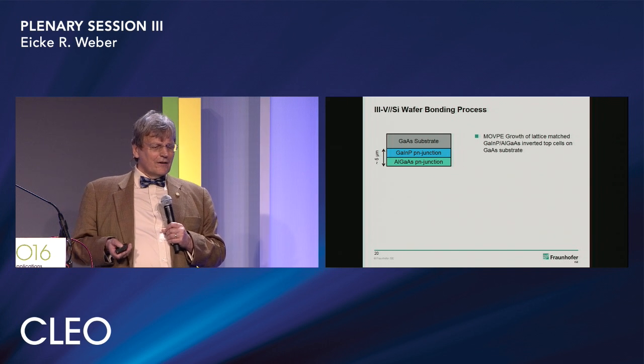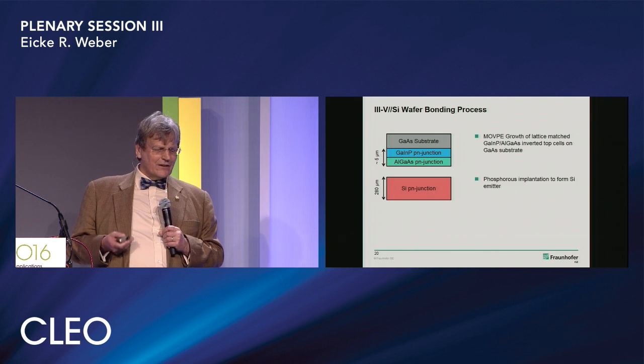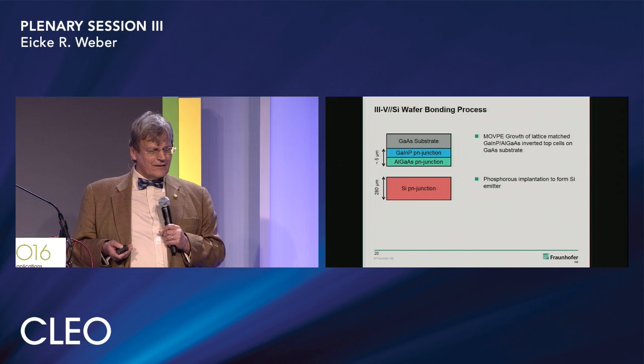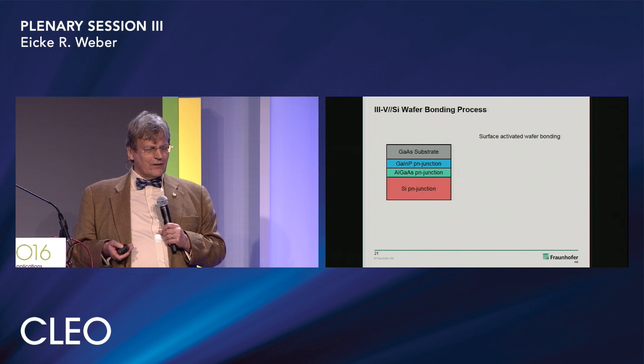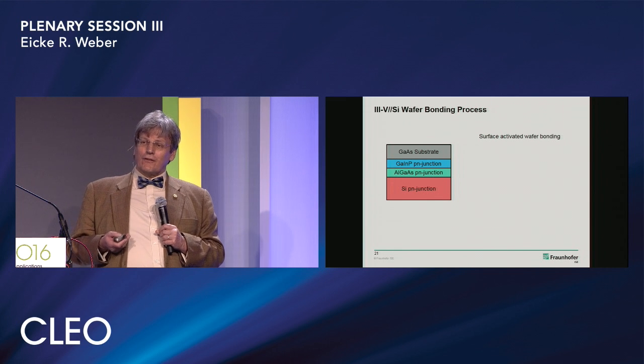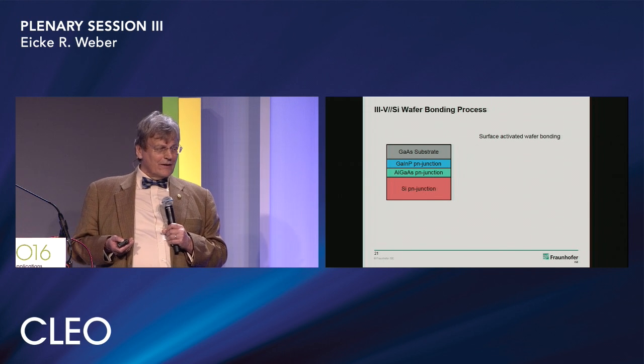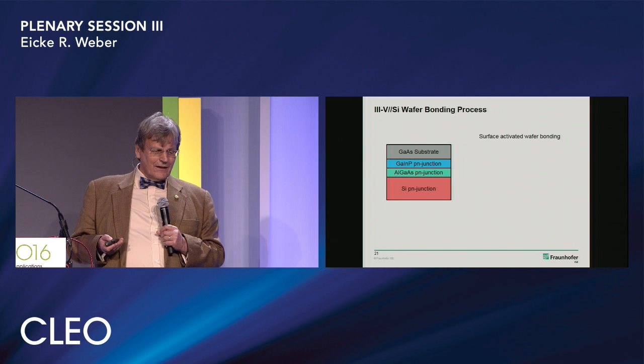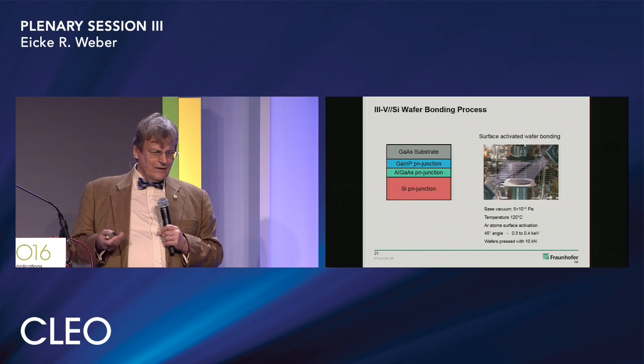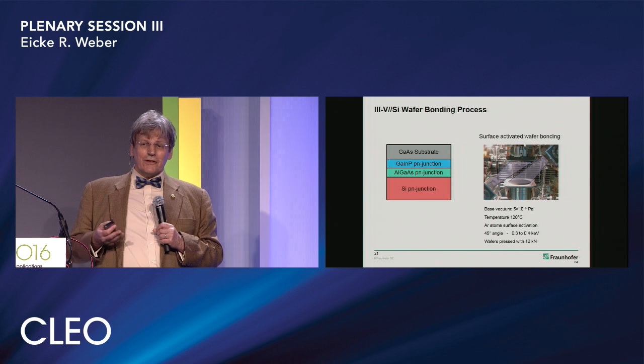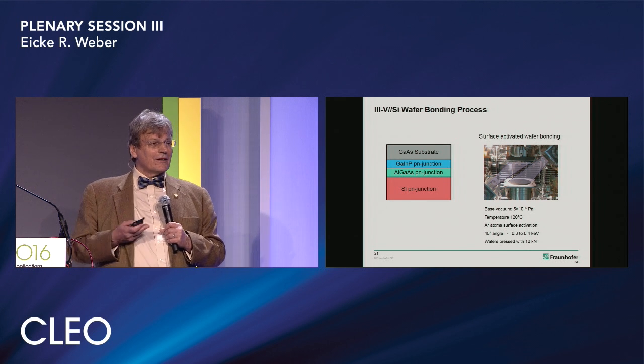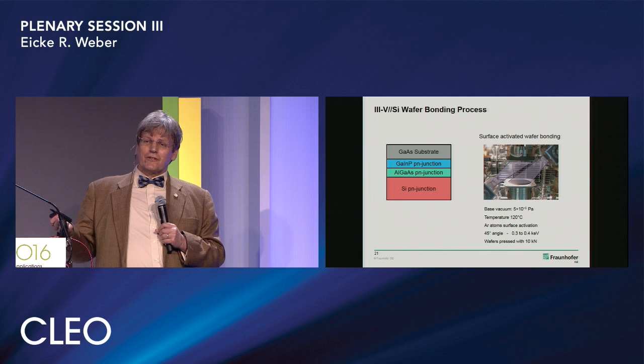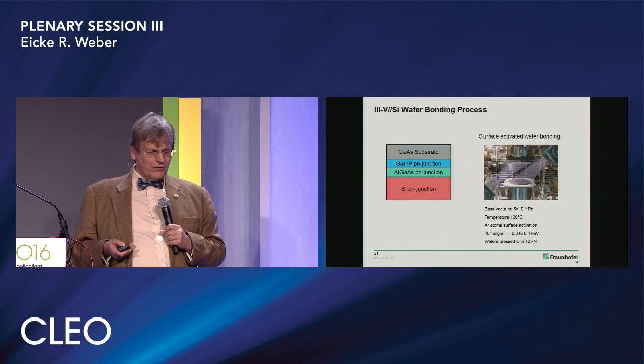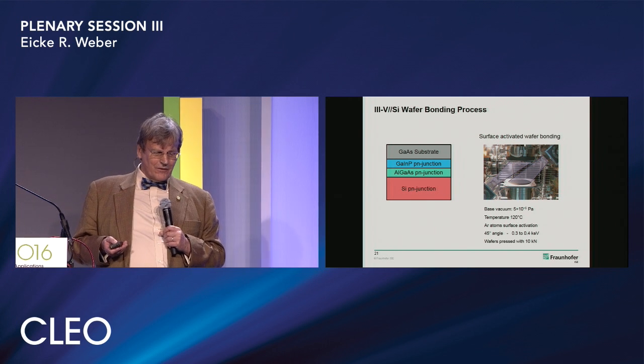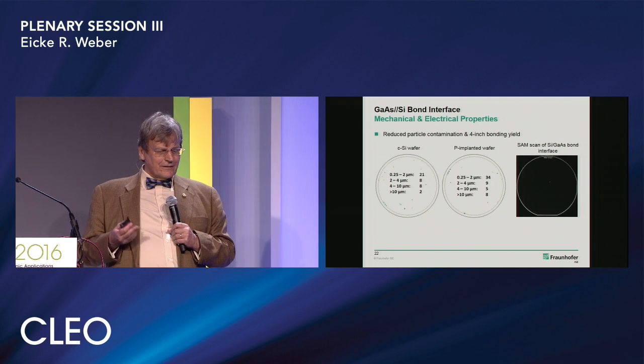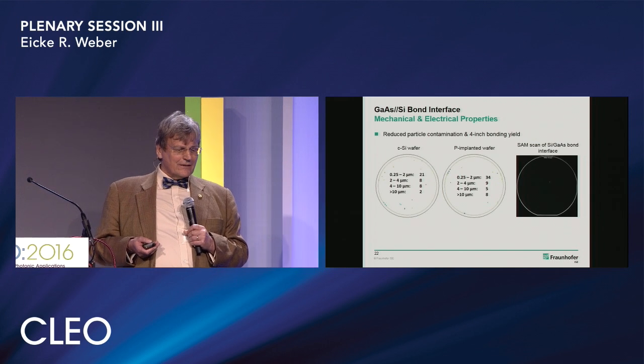We can grow III-V on one side, we can combine it with a crystalline silicon solar cell, and we use wafer bonding in order to create one structure, a two-terminal device, which can be used at the end of the day like any silicon solar cell. Of course, we need to use the experience which has been gained in wafer bonding in the silicon world. 200 millimeter wafers can be today bonded without any problems, and larger diameter wafers are being worked on. This is a technology which is already well established.